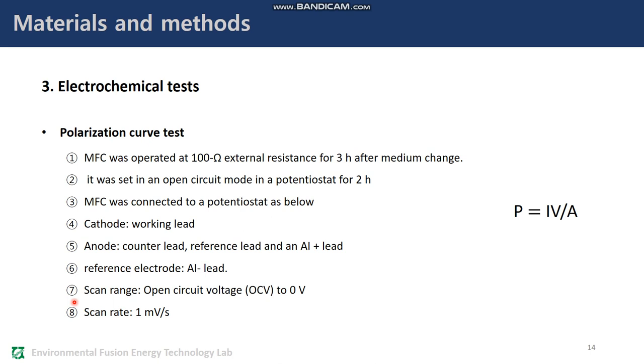Polarization curves were recorded through the linear sweep voltammetry technique by decreasing cell voltage from open circuit voltage to zero voltage with a scan rate of 1 mV per second. Power densities were calculated by using the following equation, where I is current, V is voltage, and A is cathode area. Internal resistances of anode and cathode were obtained from the slope of the linear part of polarization curves. Polarization curve measurements were performed in duplicates.